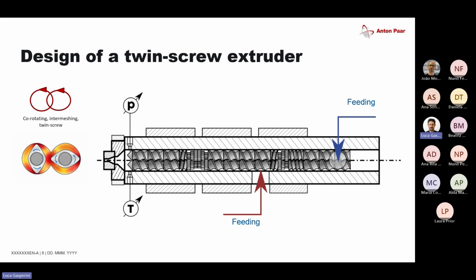And then we get a large pressure drop once the material goes over the backwards conveying elements, and we have a low pressure again here, which allows us to feed another material inside. At the end we have the same, another kneading block with a backwards conveying element. When the pressure is low, we could in theory also put a degassing port inside if it's needed.